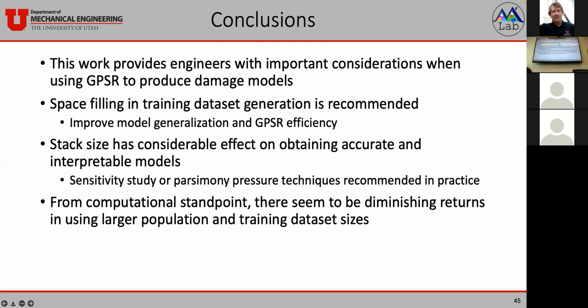Getting more into the specifics, we recommend space filling. This is shown in practice to improve model generalization as well as GPSR efficiency. We also showed that stack size has a considerable effect on obtaining accurate and interpretable models. So in practice, you might want to perform a sensitivity study on stack size or use parsimony pressure techniques. These add a regularization term to the fitness metric, sort of trying to pressure less complex models to evolve. And then finally, from a computational standpoint, there were diminishing returns from using larger population sizes and training data set sizes. So again, in practice, finding a happy medium there would be recommended.